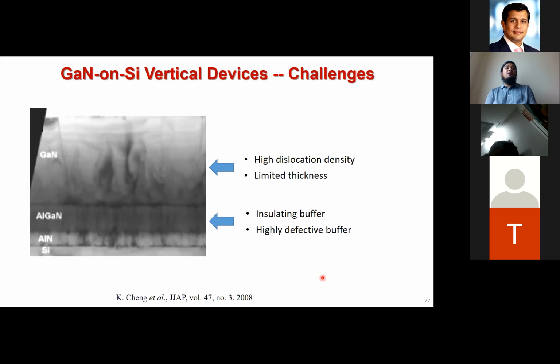Here, as an example, I'm showing a cross-section TEM image of gallium nitride grown on silicon from literature. On the bottom, we have this silicon wafer, and gallium nitride is grown at a very high temperature, 800 to 1000 C. When we grow at a high temperature, we also need to consider that different materials have different coefficients of thermal expansion. Since they have different lattice constants and different coefficients of thermal expansion, we need to put something in between to make this transition for the growth to happen. As a result, we have to include aluminum materials like aluminum nitride and aluminum gallium nitride in between silicon and gallium nitride.